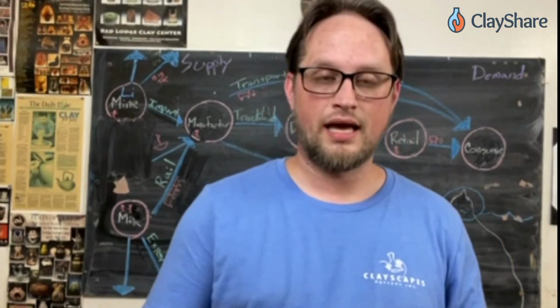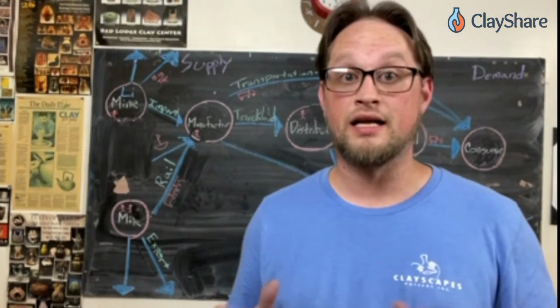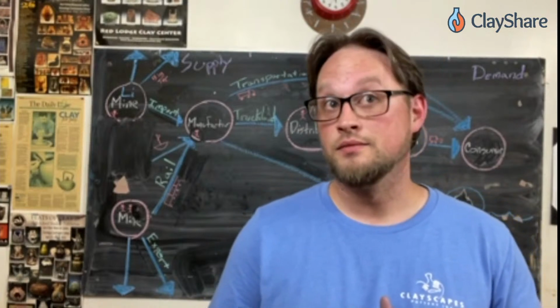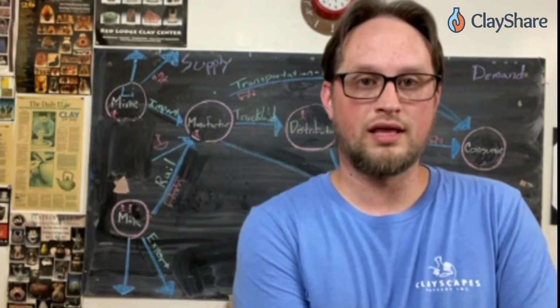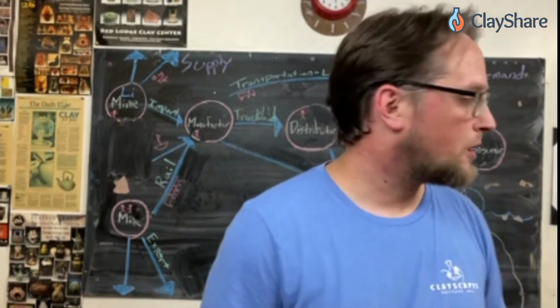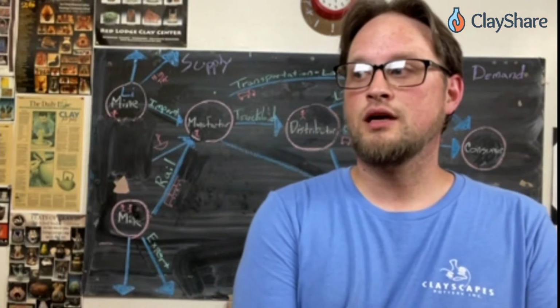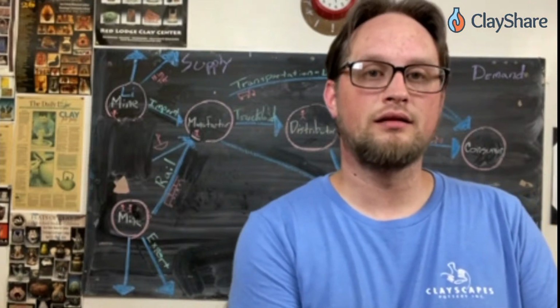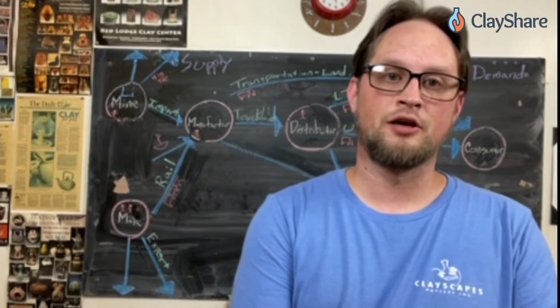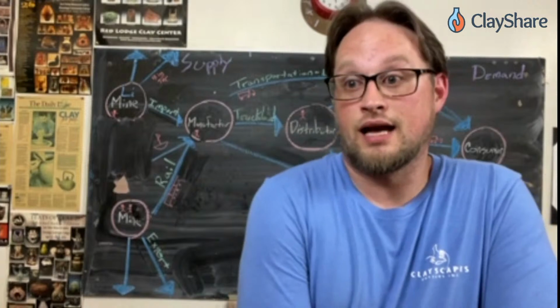Iron is not as bad because iron is a lot more forgiving than some of the other ingredients. Cobalt and copper, I will see sometimes 2 to 3 changes a year in what they look like in the raw state. So to go back 20 years, that cobalt would be completely different. We won't use old ingredients because you can't replicate the results that you get with them, because those ingredients are gone. Even though it's the same ingredient, it's still 20-year-old iron oxide, and that iron oxide is going to be different.